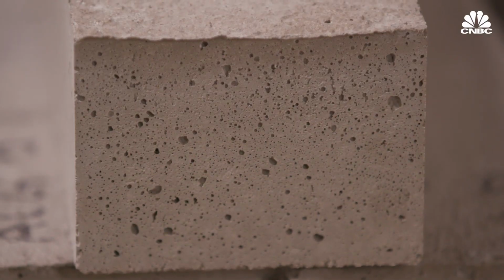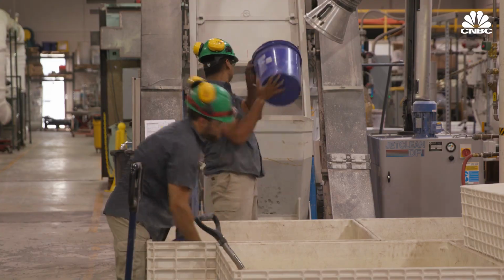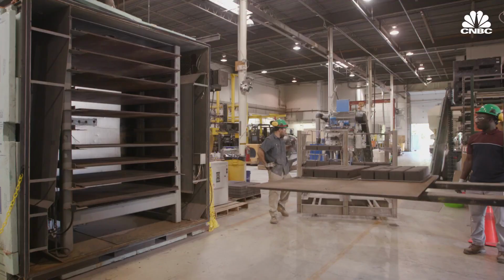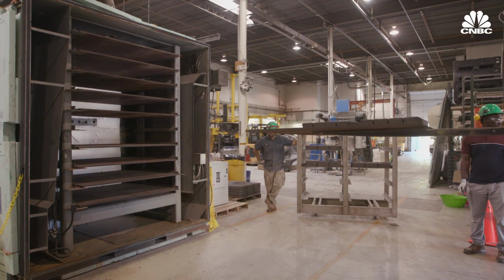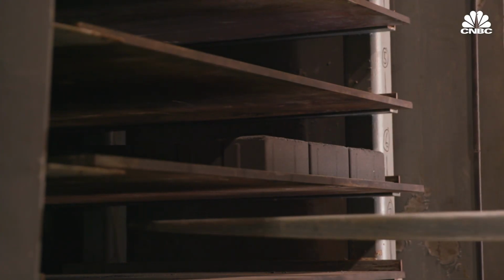When you make Solidia cement, we are cutting the CO2 emissions at least by 30%. And when we cure Solidia cement, when we make the concrete, we add an additional 20-30% of CO2. We consume it during curing. So this adds up to 50-60%, and depending on the formulations, our CO2 savings can go up to 70%.